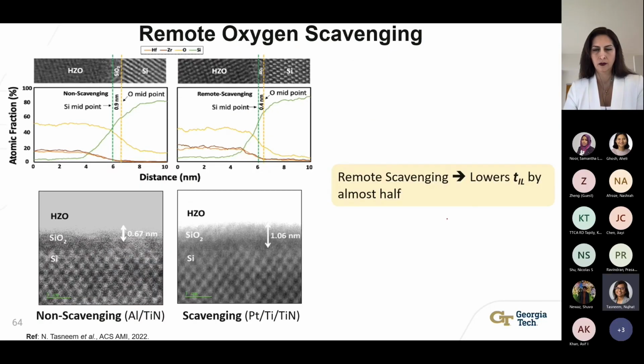So for this experiment, we fabricated two ferro MOS caps, one with a non-scavenging top electrode, aluminum titanium nitride, and another with the scavenging top electrode, platinum titanium nitride. Now, with the help of our collaborators in UCSD, we were able to do EDS line traces and acquire the STEM images for both the samples. And the results show that remote scavenging can in fact lower the interfacial layer thickness by almost half.